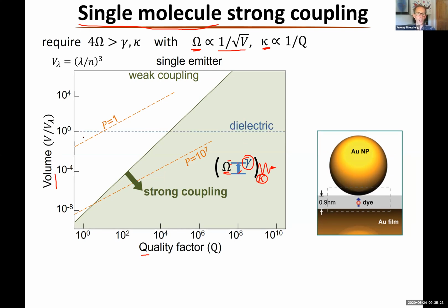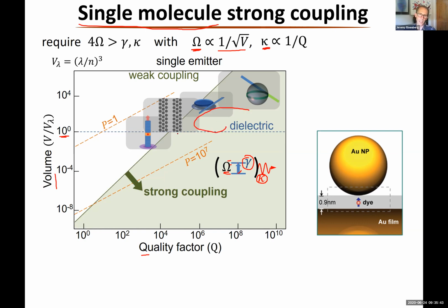So this is the dielectric boundary, essentially what I showed you before, that the volume when I'm using dielectric confinement can't get below that level there. And all of the typical ways of confining the light are stuck up here, right? Because the volume of the cavity is not small enough, which means to get strong coupling, you've got to be in this domain here. And so you need to have very high Q factors. But the other thing you need is you need to be at very low temperatures.